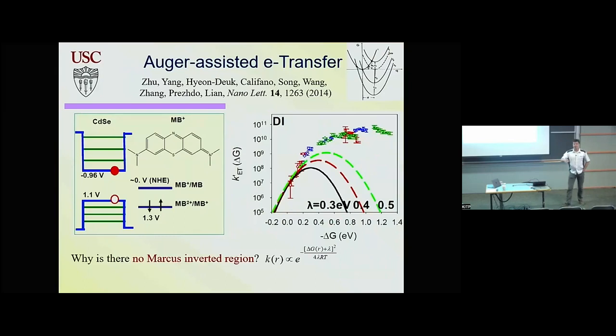Back to Auger processes and now transport. In this case, I'm discussing experiments of Tim Lian at Emory, and I'm talking about transfer of charge from a quantum dot to a molecule. This molecule is designed such that the level of the molecule is actually below the conduction band edge of the quantum dot. And the surprising fact was that, in chemistry, there is this famous Marcus theory that was developed back in the 50s, and then in the 80s this so-called inverted Marcus regime was demonstrated, which was surprising, and then he got the Nobel Prize when this was demonstrated experimentally.